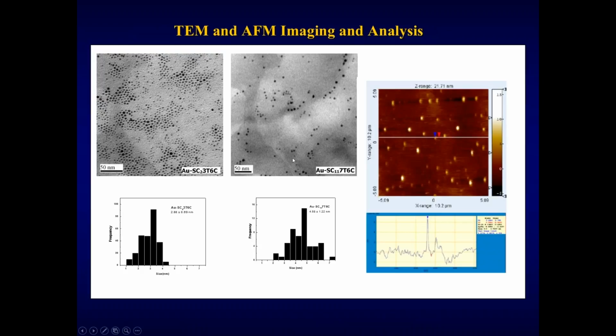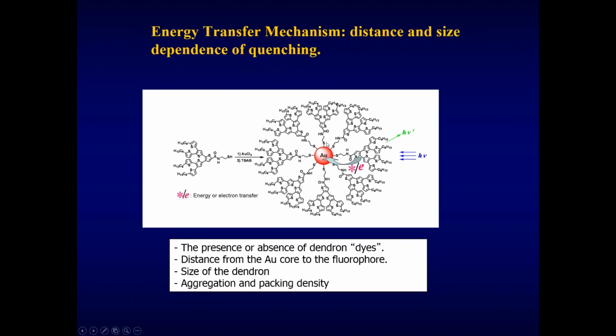So notice here that the thio group will then be capped on the gold nanoparticle surface to produce nanoparticle hybrid dendrons that look like this. So the gold nanoparticle core then should be surrounded by a finite number of the 7T or 3T derivatives with different chain lengths. In this case, TEM actually was an effective tool to look at the dispersity through this histogram, as well as the effectiveness of the direct synthesis of the gold nanoparticle hybrid dendron. But here you can see the equivalent AFM. So what's interesting here is both AFM and TEM have consistent results in terms of size. AFM actually gives us a direct height measurement, whereas the TEM gives us a histogram of the nanoparticles, and the widths can be directly measured from the image.